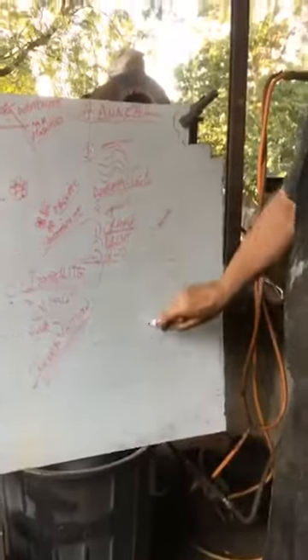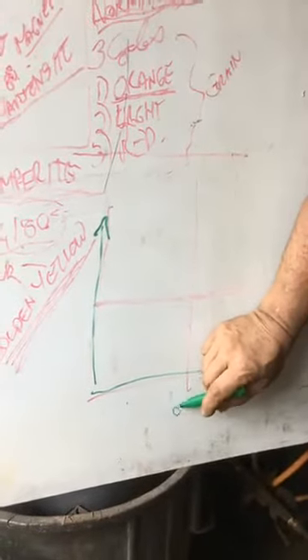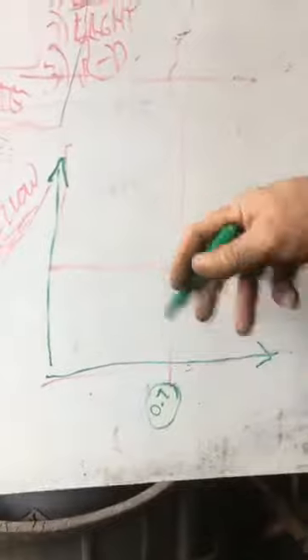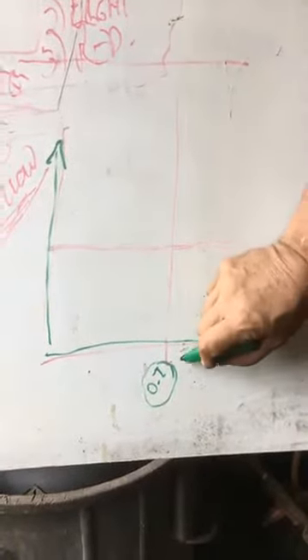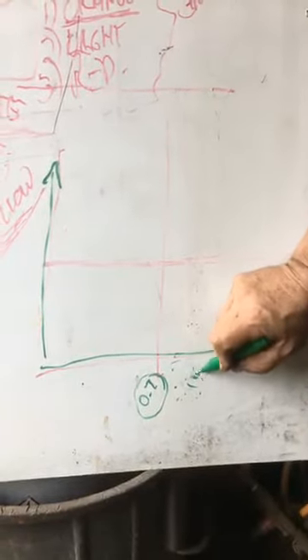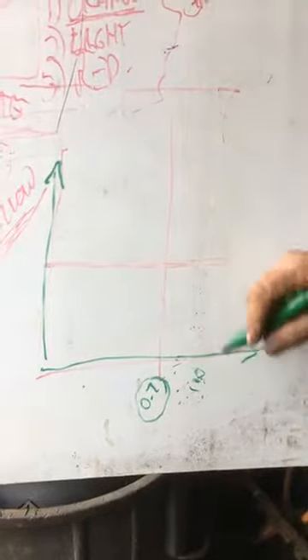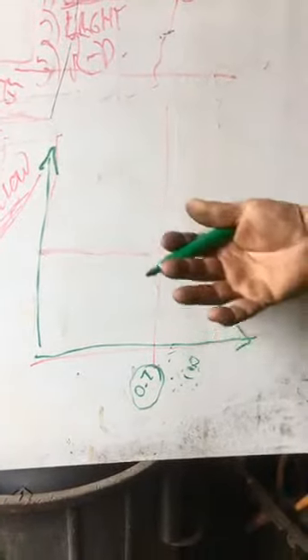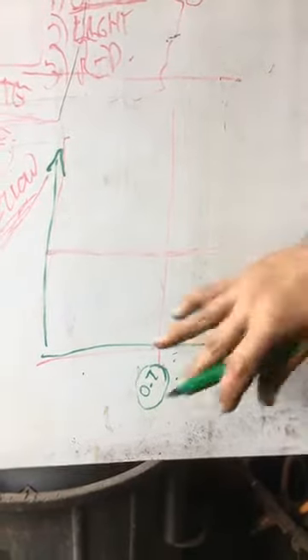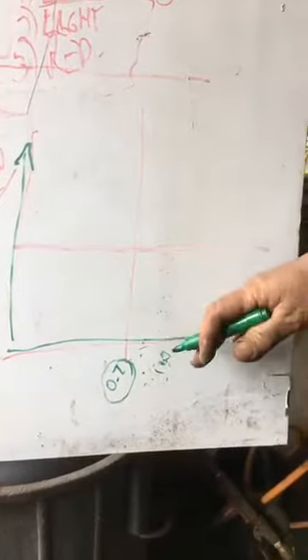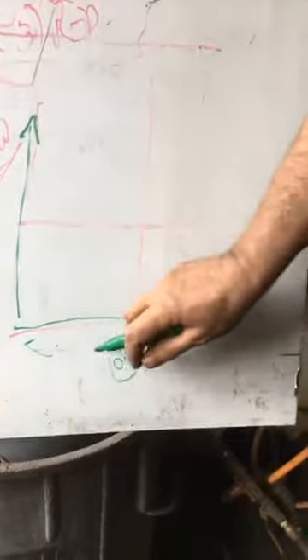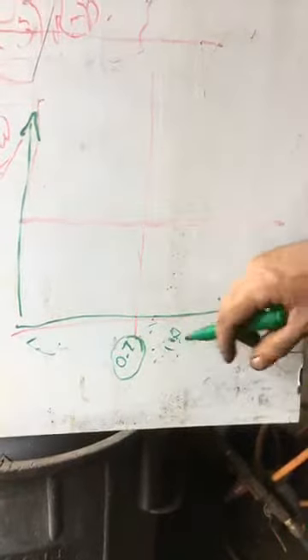So just going to show you this graph quickly. Okay, so that's temperature. That's carbon content. At 0.7%, plain carbon steel is fully saturated with carbon. So any carbon left over, so like at 1%, is going to attach to other alloys in the steel, and that's where you get your carbon tungsten blades, for example. It's going to attach to the tungsten and make that harder. It's first going to saturate the ferrite, and then it's going to attach to other alloys in the blades. Below 0.7%, it's all going to saturate the ferrite first, and above it's going to attach to other alloys.